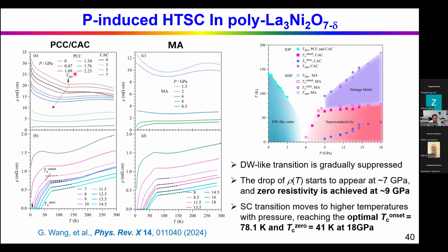So basically, the pressure suppresses this density wave transition, and the superconductivity appears above 6 gigapascal. But the zero resistance temperature, TC0, appears at much higher pressures. So in the polycrystal samples, we can reach zero resistivity easily, and it's very reproducible. This is one advantage of the polycrystal sample. It's uniform.